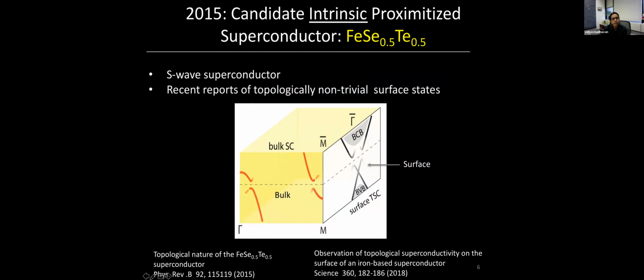So in 2015, there was this proposal that FeSeTe has in fact one band that is inverted at the gamma point. And because of that, it's topologically non-trivial. And due to its topologically non-trivial nature, it has topological surface states. So the beauty of this, of course, is that since this is a superconductor, you have this kind of intrinsic proximitized superconductor where the topological surface states become superconducting by proximity effect. And now you have in one system this ability to realize Majorana fermions.